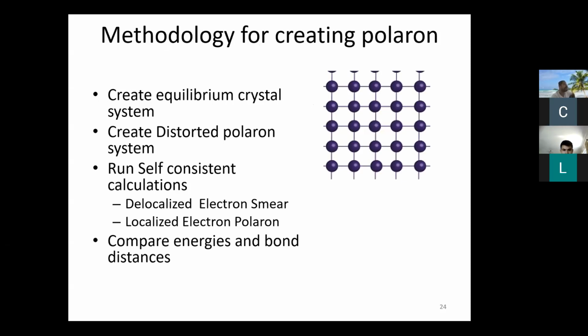In terms of the methodology for creating a polaron in these cells, I basically construct a supercell. This is an example of just a model, and I can add an electron to this system. The problem with the system that I'm using, VASP, which runs DFT calculations, is that it automatically smears the electron everywhere. So you're not going to get localization, as it could fall into a local minimum of the system, even if it is preferred for it to localize.